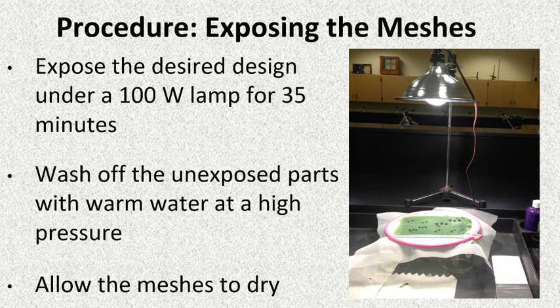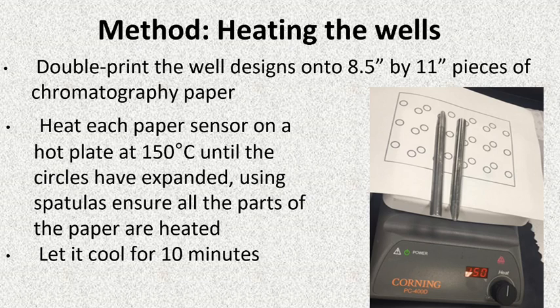Now for the actual wells that we use, these are double printed on 8.5 by 11 pieces of chromatography paper. Double printed to get extra wax on there, but you have to make sure that the wells are aligned correctly, or else you'll mess up your print. Heat each paper sensor on a hot plate at 150 degrees Celsius until the circles have expanded, using the spatulas to ensure that all parts of the paper are heated, and let it cool for 10 minutes, and voila, you have just made the base for a screen-printed carbon electrode.